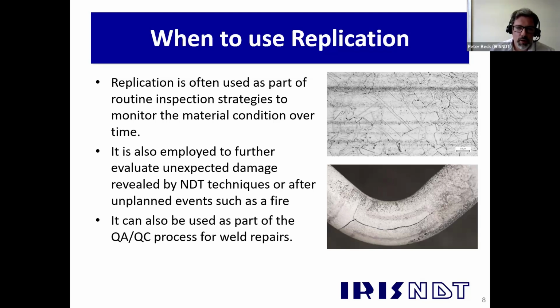So you can either just look at it as a general inspection strategy. Also, sometimes we look at things that have been uncovered by other NDT techniques. So the picture at the bottom is showing an MPI indication on a bend. So this was something that they were only going to do MPI on, and then obviously you can see the indication there. So you typically replicate the crack tips, and then you can start to understand a bit more about the degradation mechanism from that particular feature, that indication.